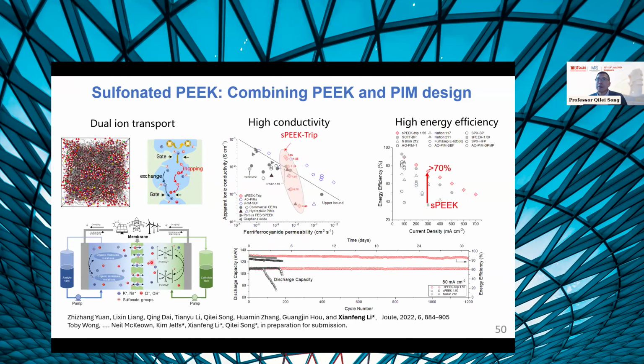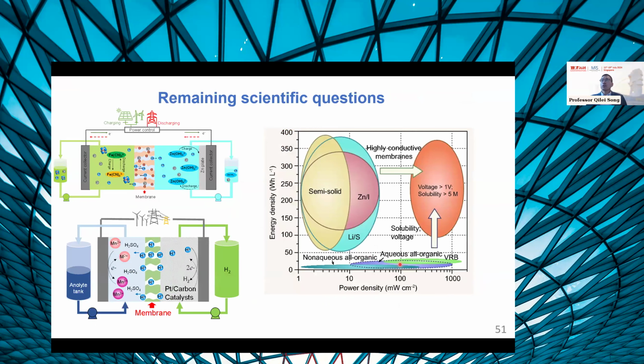And when we integrate this membrane into the flow battery, for example, organic flow battery or zinc ion battery, we always got higher energy efficiency and also decent selectivity, so the battery can be operated for nearly a month. Of course, there are remaining scientific challenges if we want to apply these membranes into new generation redox flow batteries. Especially for alkaline flow batteries, the degradation of these membranes in alkaline electrolyte is a critical challenge. We have to improve the chemical stability of the membranes.